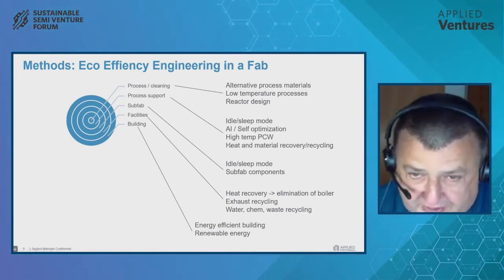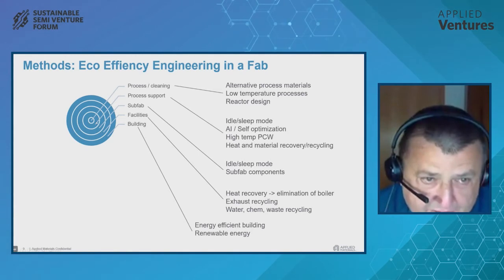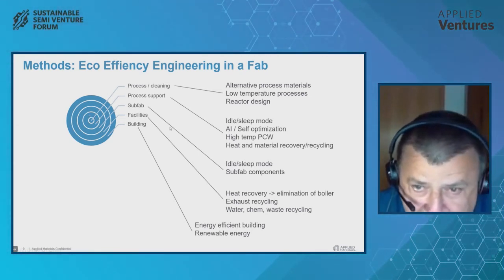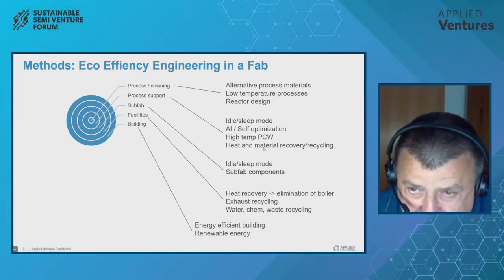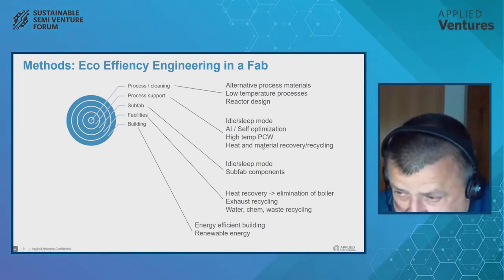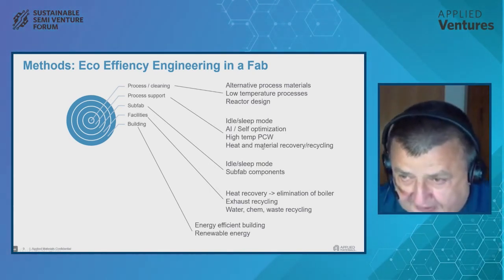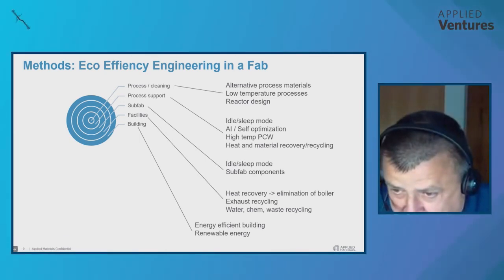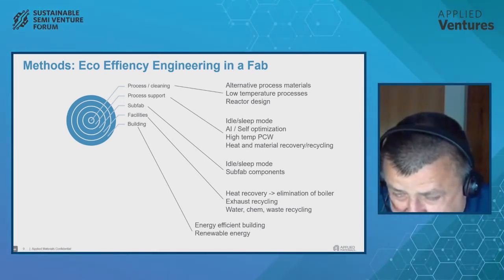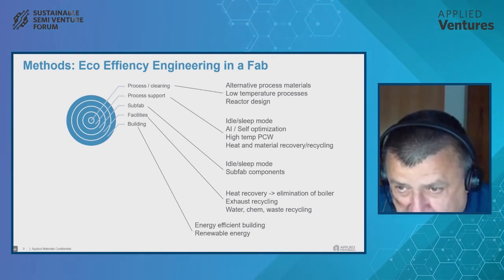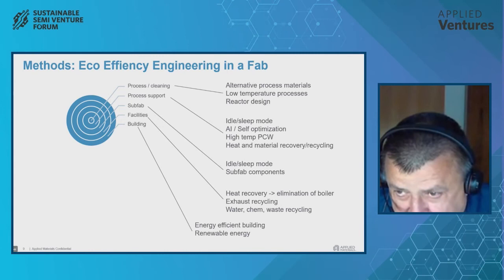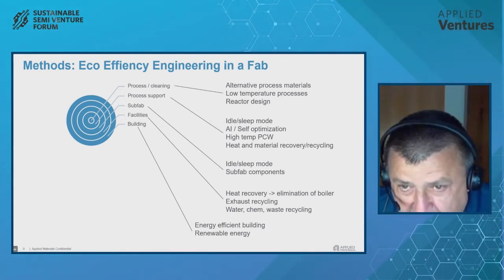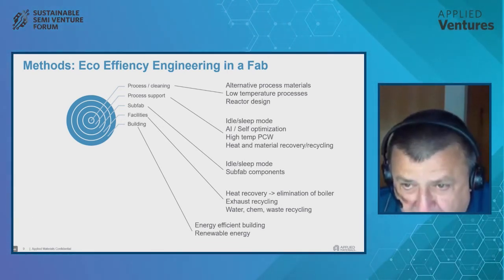Of course, you can also go and say, I'm building a reactor out of heat recovery materials, but then you need to deal with 900 degrees C, you need to deal with fluoride, you need to deal with many kinds of depositing precursors like silane, forming silicon oxide layers, so the efficiency of your reactor will always be impacted by that. So it's a difficult task. But each solution could provide a substantial improvement in the semiconductor industry.